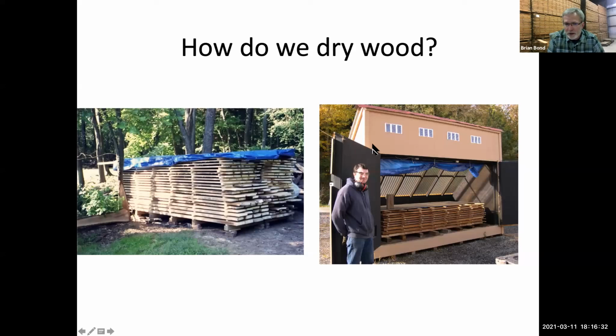One, you can typically control the conditions. So if you look at the picture of the air dried lumber, what's it doing when it's raining out there? What happens when the relative humidity is too high, right? What happens when the wind blows and blows the rain in there? I can't control the conditions of the outside environment. In the dry kiln, I can absolutely control the temperature, the relative humidity, the amount of airflow, and I can keep the rain off the wood. And I can also raise the heat enough that it'll drop the relative humidity to give me a faster drying rate. And I can control that drying rate in a dry kiln if I know what I'm doing and I use the proper techniques. So that's why we typically use a dry kiln.